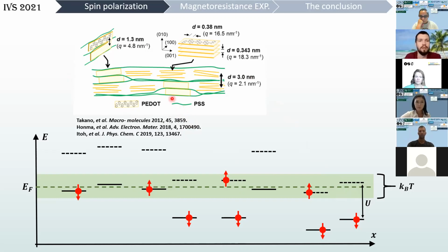It has been shown that within the solid film, the PEDOT tends to form nanocrystalline regions that are embedded in the PSS matrix. And within the nanocrystalline regions, the PEDOT segments are pi-pi stacked. Then, if we envision the hopping conduction as hopping between these nanocrystalline domains, which are actually charged, then we can expect the Coulomb correlation to take place in the system.